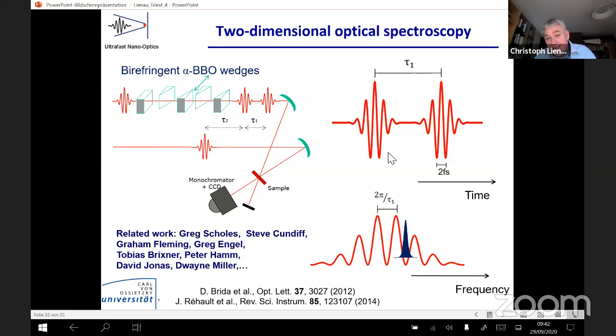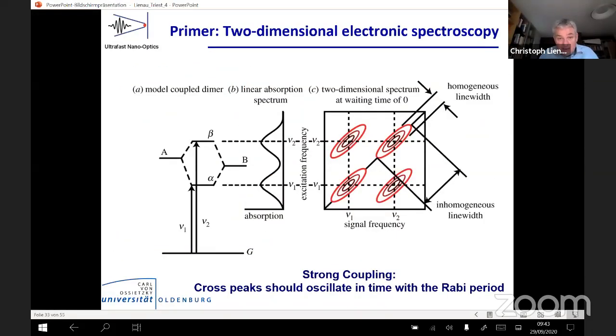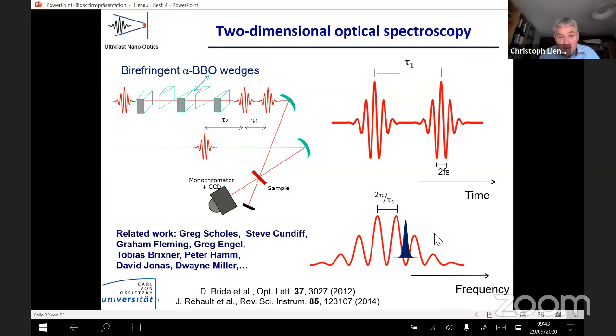So you can, and that's the essence, use a sequence of 2 ultra-short pulses to selectively excite every single different quantum state in your system, and probe its response while maintaining time resolution set by the pulse duration. So you can perform, if you wish, a highly spectrally resolved experiment probing the fate of every state in your system with a time resolution that is only set by the pulse duration of the pulse. And that's pretty tricky, but very interesting. And you can do nice things. What is done in the experiment is a bit complicated, but I will guide you through.